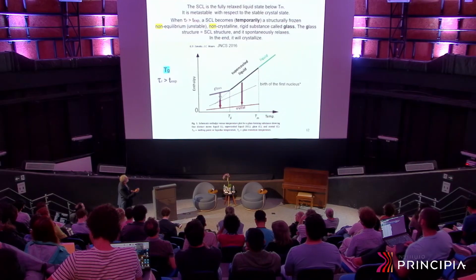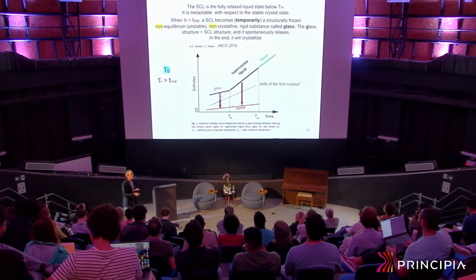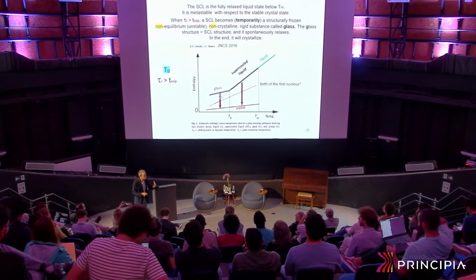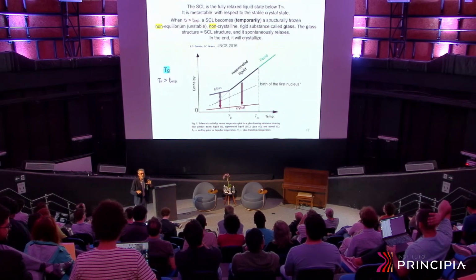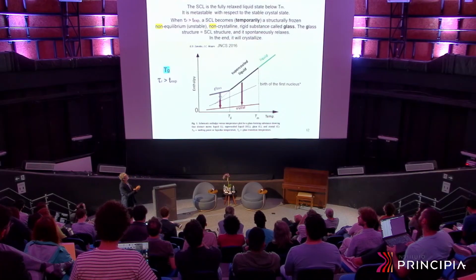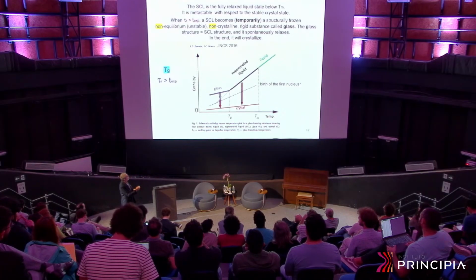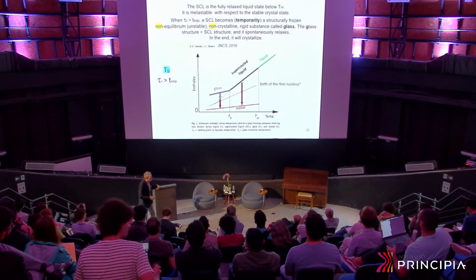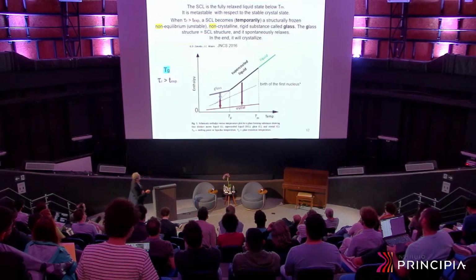You might be below the glass transition or above the glass transition. It doesn't matter. It just takes longer. All the things that happen above Tg also take place below Tg. So glasses crystallize even below the glass transition temperature.